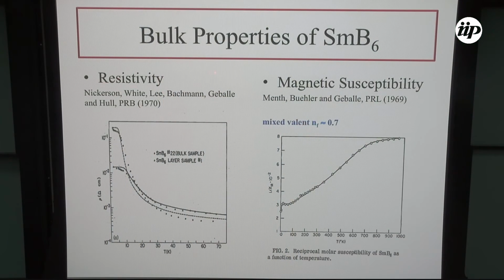Okay, so that's a simple model of topological insulators, which we'll see a little bit later. I'm introducing some of the experiments on SmB6. These go back to 1969. And what you see here is the resistivity, which shows this sort of insulating behavior. There's this peculiar behavior at low temperatures that these things plateau, and that's always been a problem.